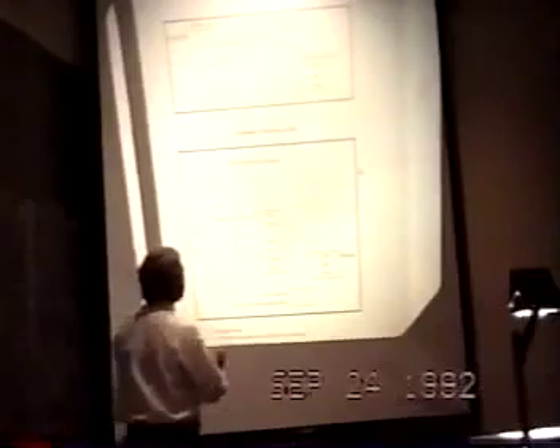We're looking for potential sources of systematic error in these terms. Temperature coefficient of platinum, we expect to know, a source of error, and do nothing about it. Heat capacity: in all but one of the experiments that I will describe the results of, water was the heat transfer fluid. Its heat capacity is well known, and its temperature coefficient of that heat capacity is well described.